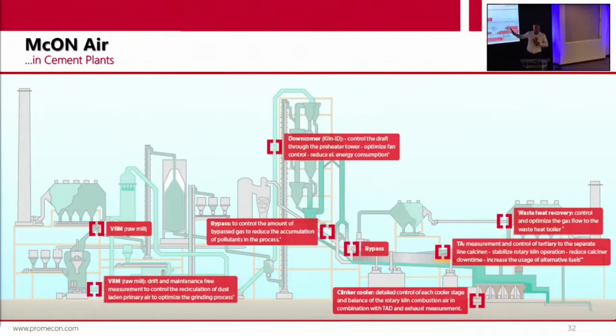We have installed many tertiary air measurements in order to optimize the mixture of tertiary air with the fuel in the pre-calciner. And then we can also measure the total air balance over the clinker cooler. So you can optimize clinker cooling. And waste heat recovery is another thing. These are the most popular ones. There will be more. There's bypass measurement. In a cement plant, there's gazillions of things.